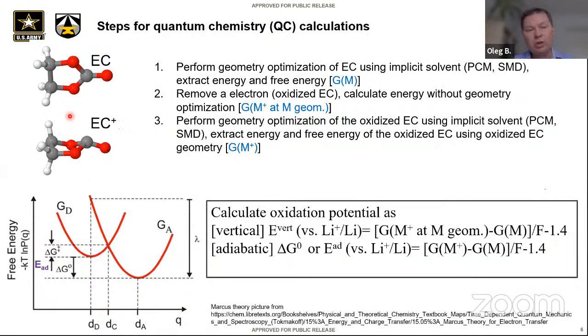However, we can perform a geometry optimization. When we perform geometry optimization, the geometry deforms significantly. There is a deformation energy, and that will be the free energy at the cation geometry. So we can calculate two oxidation potentials. One I'm going to call vertical, when the free energy is calculated at the neutral molecule geometry with the electron removed, minus the energy of the neutral molecule, divided by the Faraday constant, minus 1.4. The other is the adiabatic one, when we perform geometry optimization for both species.